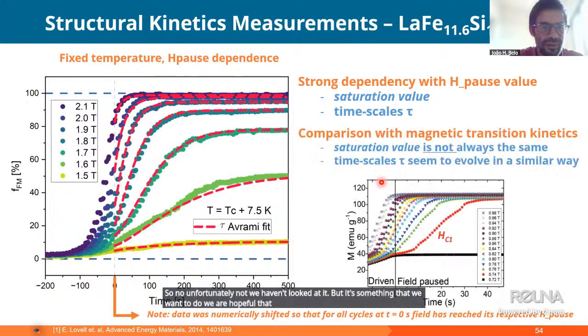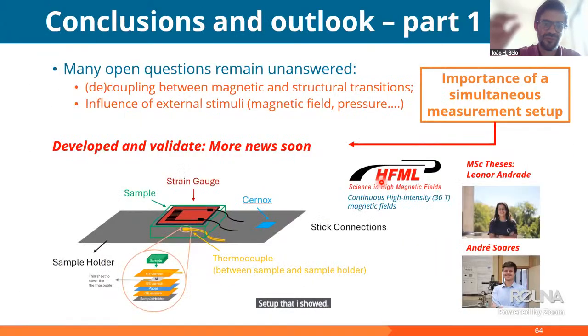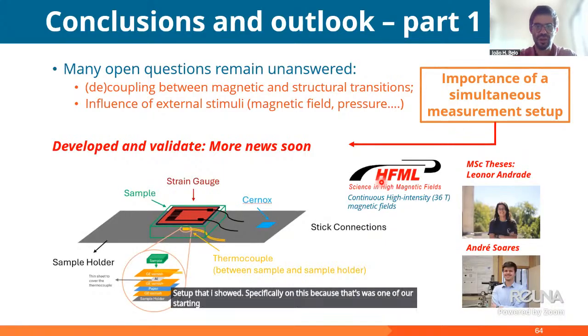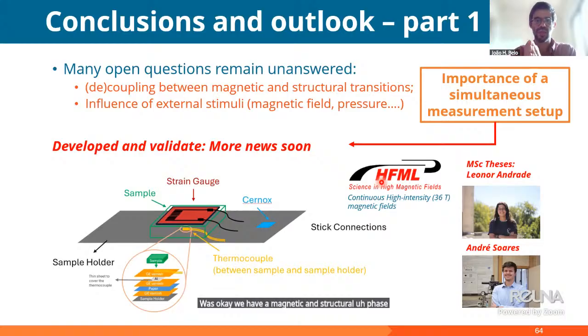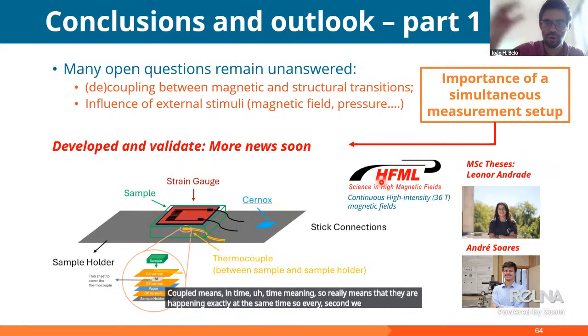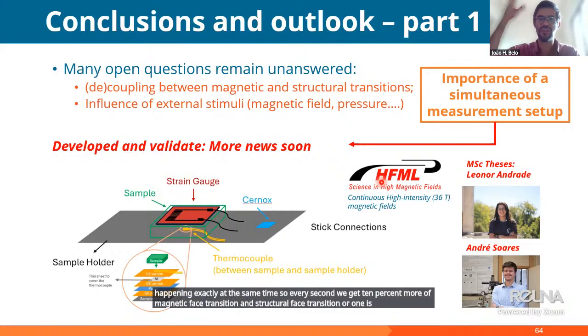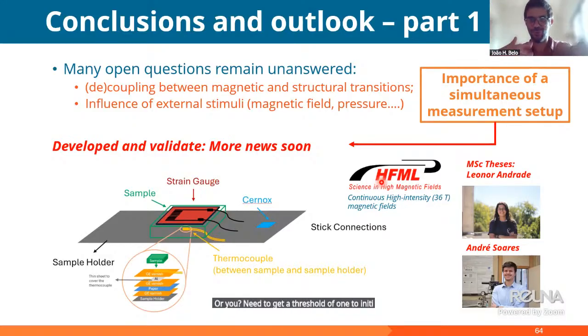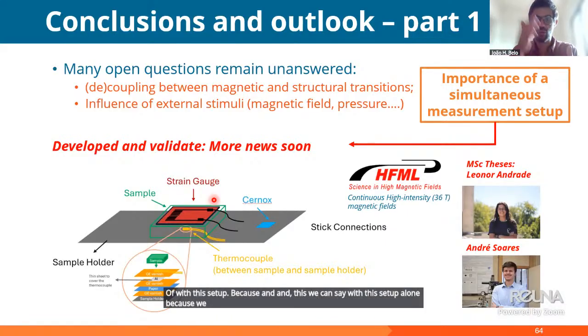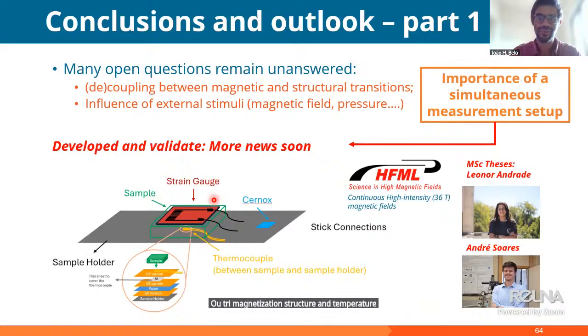We are hopeful that now, with the setup that I showed, we can address this, because that was one of our starting questions. We have a magnetic and a structural phase transition. They are supposed to be coupled, but what does this coupling mean in time? Does it mean they are happening exactly at the same time, so every second we get 10% more of the magnetic and structural phase transition? Or is one lagging the other, or do you need a threshold of one to initiate the other? We are now getting data with this setup, and we can say this with this setup alone, because we are measuring all three simultaneously: magnetization, structure, and temperature. Sorry, the simplest answer was to say no, we haven't looked at it, but we are very eager to do it.